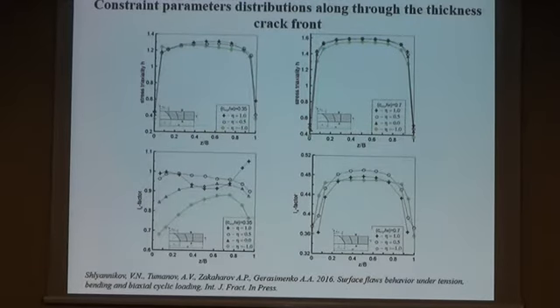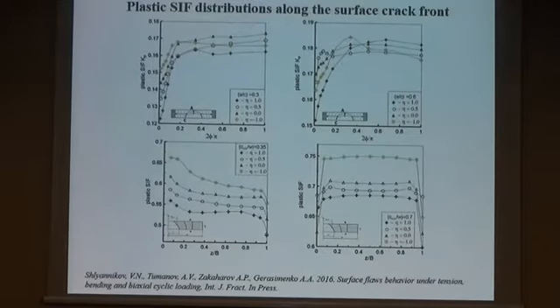So, as mentioned above, on the basis of solution for SIF, we calculated the distributions of plastic stress intensity factor along the surface crack front and along the through thickness crack fronts in cruciform specimens for all considered types of biaxial loading. So these numerical results were used for crack growth rate interpretation.